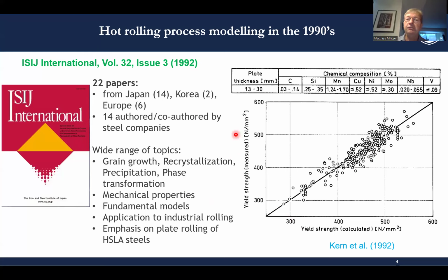A summary of what was achieved is shown here by the contributions from Kern and co-workers from Germany, who calculated the yield strength for a range of plate steels with different thickness and different compositions, so low carbon steels microalloyed with niobium and also with vanadium. You see what the predictive capability at the time was, and also what the strength grades were, between 300 and about 550 or so megapascal. And many of these steels are also still important today.